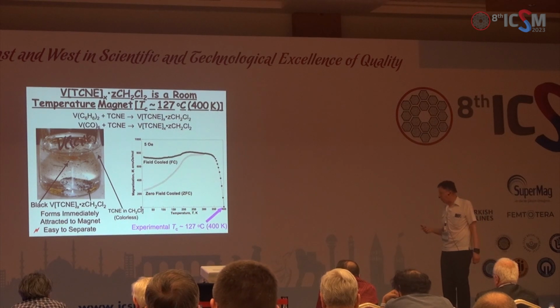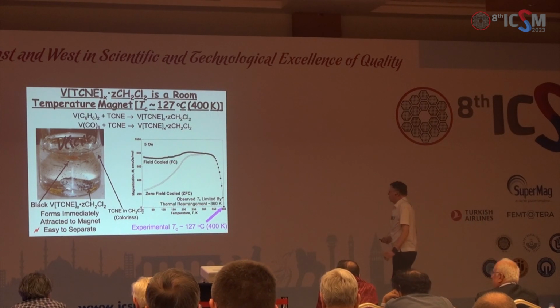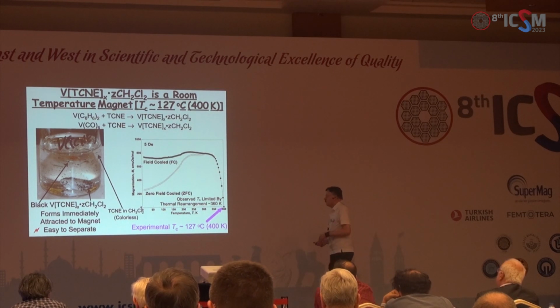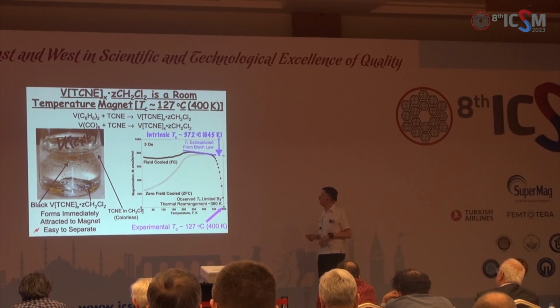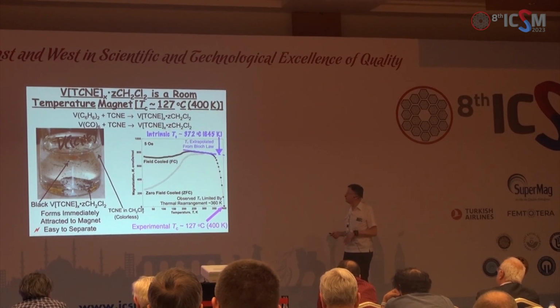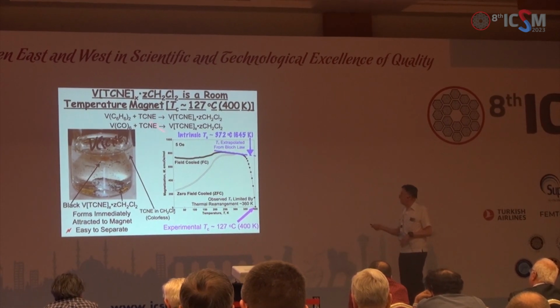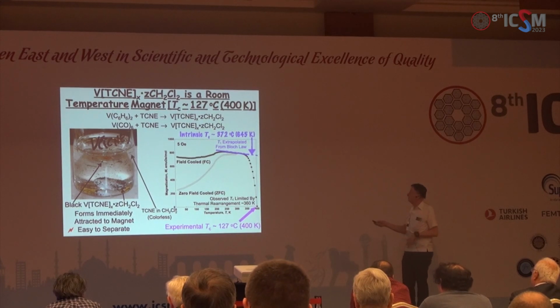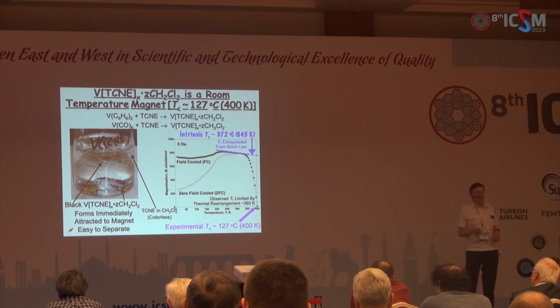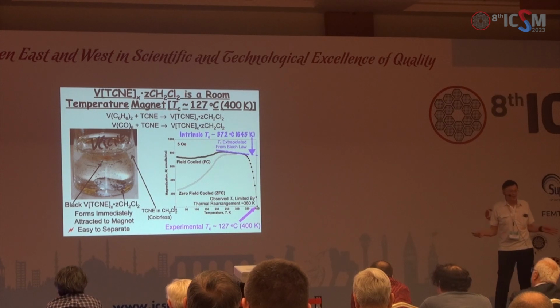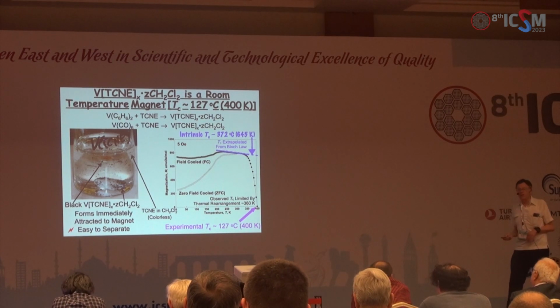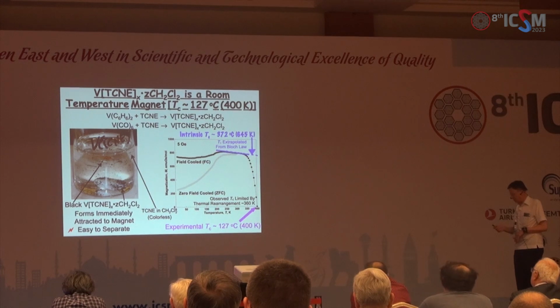This material unfortunately has a thermal rearrangement around 360 Kelvin, which limits the observed critical temperature. If you play physicist for a moment and use the Bloch law, you can extrapolate based on the data here to find that it magnetically orders at 645 Kelvin, 372 degrees centigrade. We can't achieve that experimentally because of the disorder, but that's the intrinsic value this material exhibits.